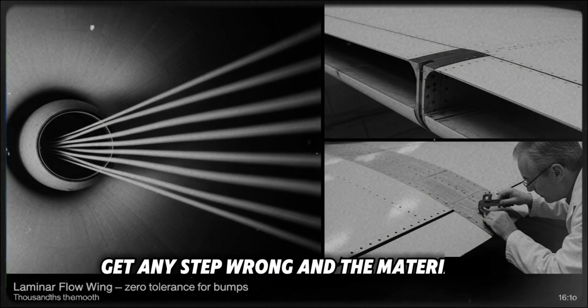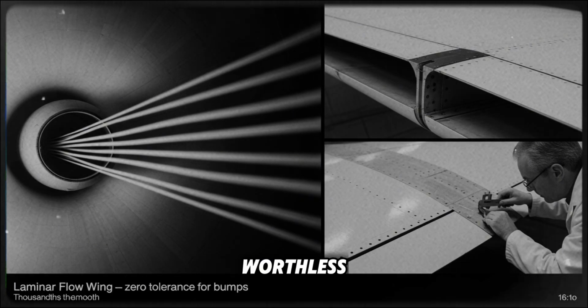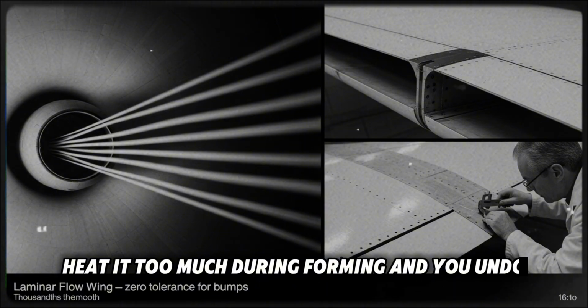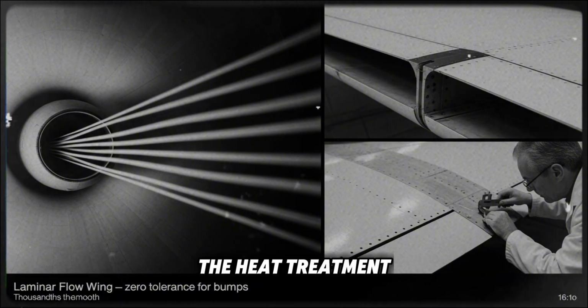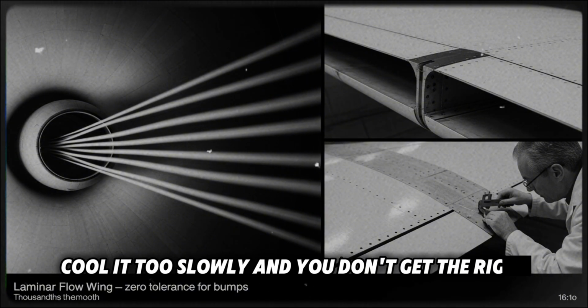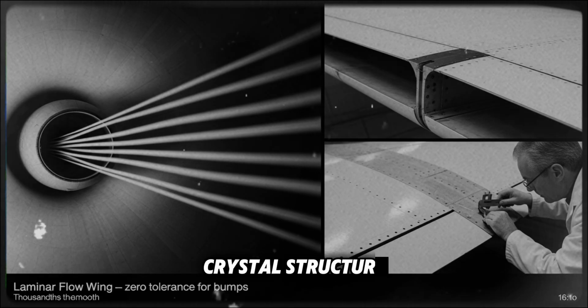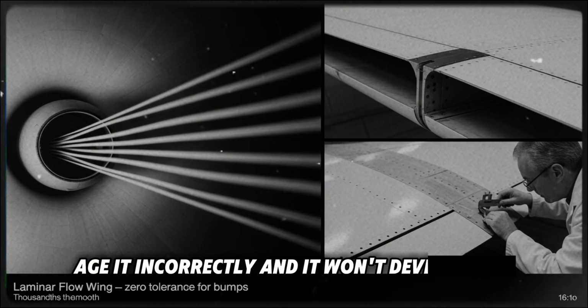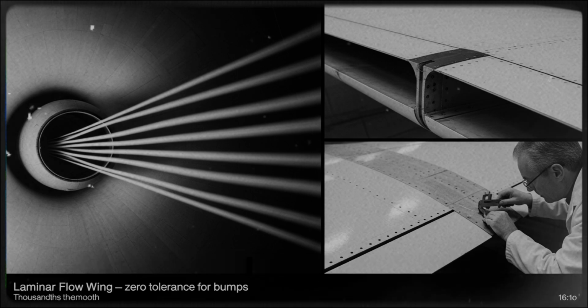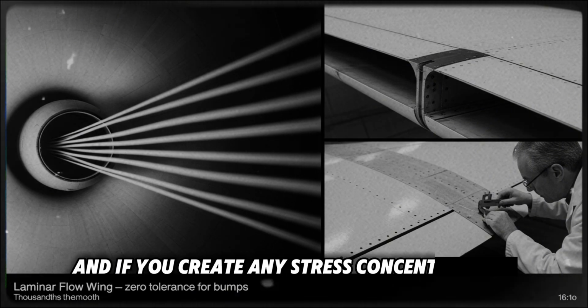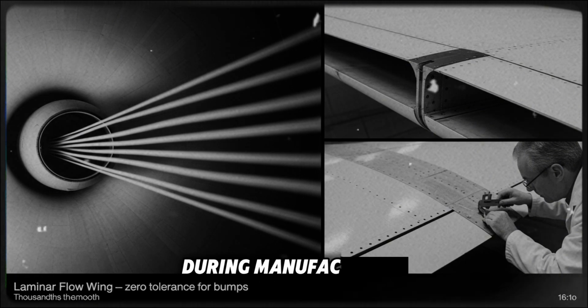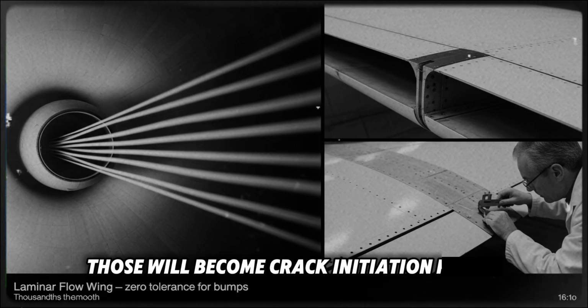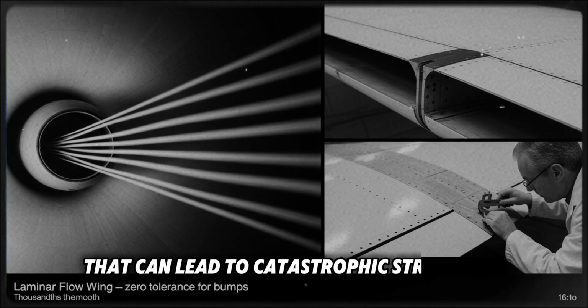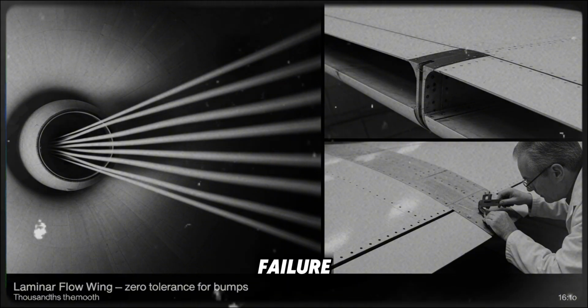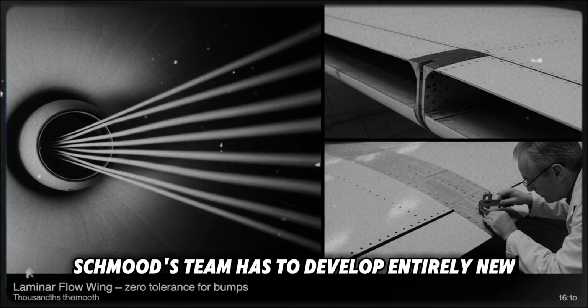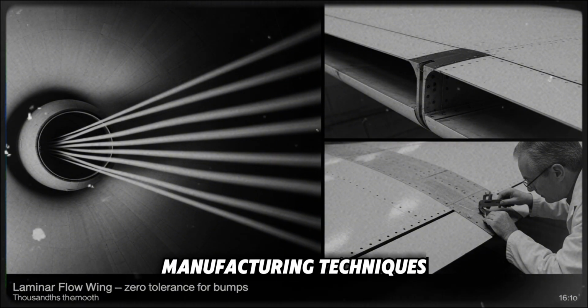Get any step wrong, and the material is worthless. Heat it too much during forming, and you undo the heat treatment. Cool it too slowly, and you don't get the right crystal structure. Age it incorrectly, and it won't develop full strength. And if you create any stress concentrations during manufacturing, those will become crack initiation points that can lead to catastrophic structural failure. Schmood's team has to develop entirely new manufacturing techniques.